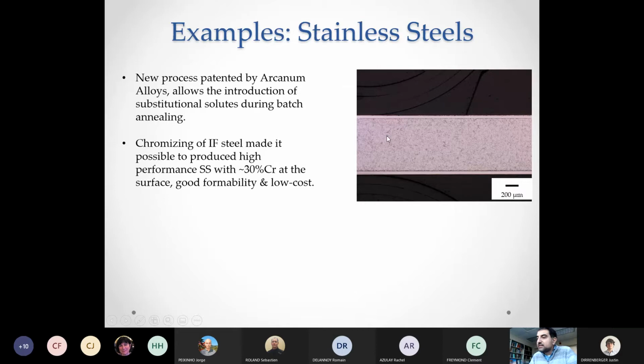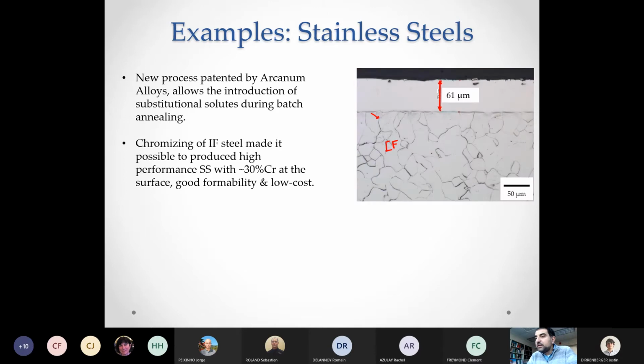So what you're looking at in this diagram, on the inside here is more or less an IF steel, and they choose an IF steel because it has very good ductility and it's also very low in cost. And what they were able to do was to introduce a high chromium layer on the surface. And if we zoom in, you can see here there is about 60 microns of high chromium region here. The chromium content in this area is about 30%.